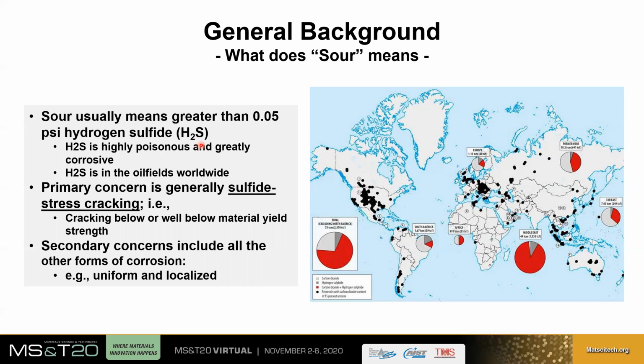So typically, the first precaution is, hey, we need to be careful about cracking, namely sulfide stress cracking. Essentially what happens is when you have a sour environment and equipment experiencing tensile stresses, if the material selection is not done appropriately, or the design is not done appropriately, for example, with low stresses, you could have cracking well below the material's yield strength. This is actually the biggest concern we typically have.